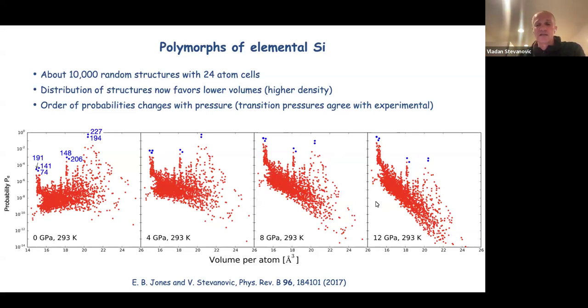It is kind of an accident that these pressures, where you see probabilities overcoming other probabilities, correspond well to experimentally measured pressures. I still have no real explanation for that, but it's an observation that every time we get a situation like this, we seem to reproduce transition pressures fairly well, without even plotting equations of state and doing the common tangent, just from the probabilities alone. But I'll leave that open at the moment.